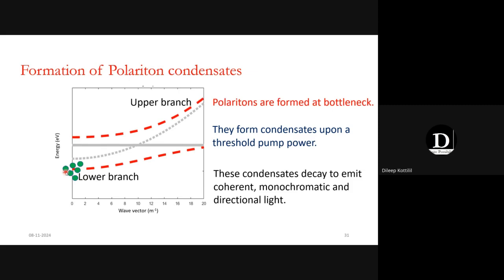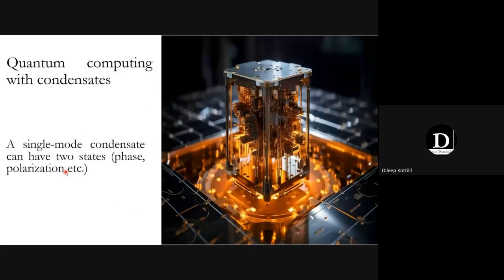So these are Bose-Einstein condensation, and the decay of this Bose-Einstein condensate results in a lasing-like effect. So these are called polariton lasers. So these are new types of lasers. And the important advantage is that compared to the normal lasers, we don't need much energy to excite this condensate. So we can still operate all these. It's very power efficient. We can operate at microjoules per centimeter square.